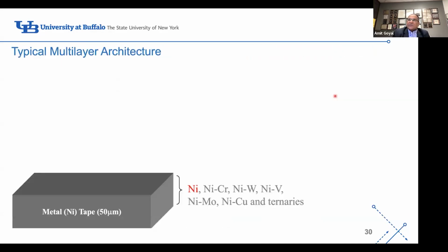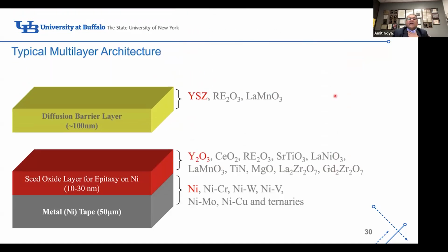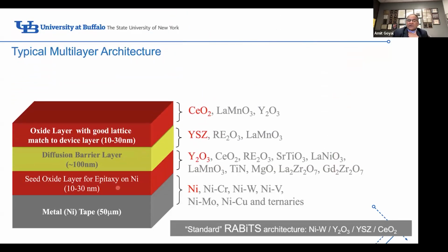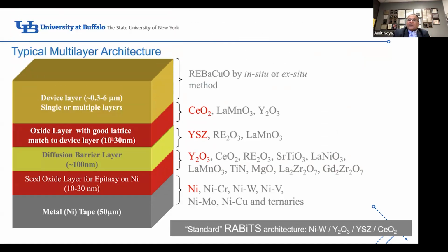So what we have in the RABiTS process, we have a metal tape, the composition of which we can choose, and we create effectively a single crystal out of it. We deposit the oxide layer, the first oxide layer, which gets the right orientation. We deposit a diffusion barrier layer. We deposit a lattice match. That is the RABiTS configuration. On top of that, we deposit a superconducting layer. And the atomic configuration is all the same all the way across these layers.